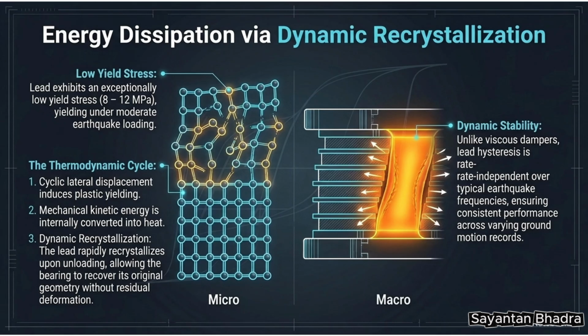Energy dissipation via dynamic recrystallization. At the material micro level, energy dissipation in the lead plug is governed by dynamic recrystallization, possessing an extremely low yield shear stress of 8 to 12 MPa. Lead undergoes plastic yielding under moderate cyclic lateral displacement. Mechanical kinetic energy converted during shear loading is dissipated internally as thermal energy.